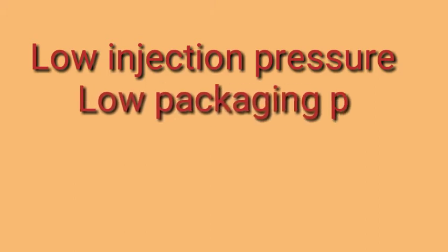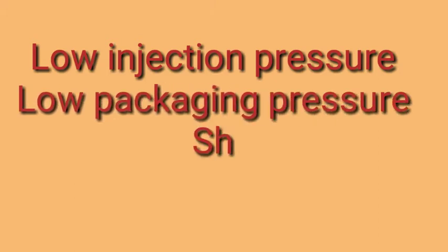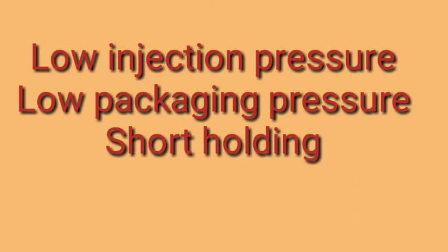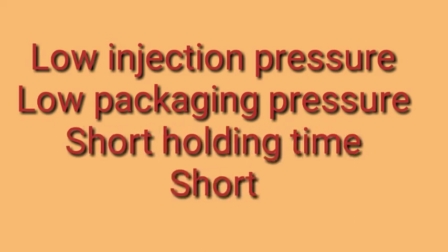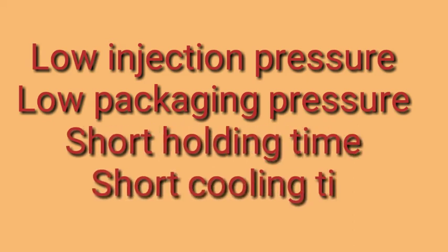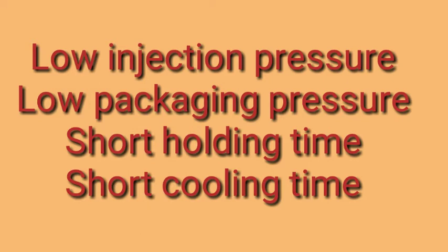Low injection and packing pressure. The other cause will be short hold time and short cooling time due to mass production to meet the customer requirements. High melt or mold temperature, that is also one of the causes of the sink mark.